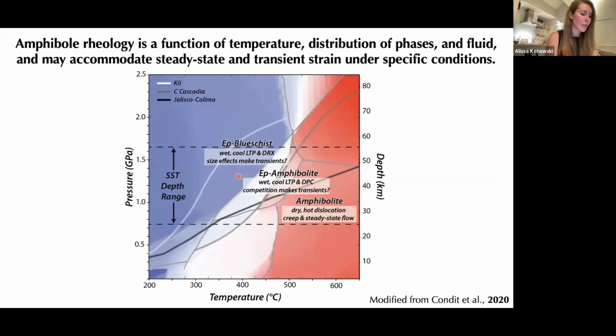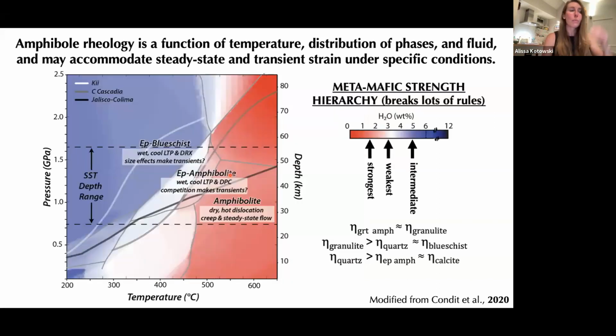So now I'll just wrap up quickly with what we've learned. I hope I convinced you that amphibole rheology is a function of temperature, distributions of phases, and water content. For the highest temperature samples, we have dry, hot dislocation creep that may facilitate steady state flow, while the other colder amphiboles with evidence for low temperature plasticity and diffusion accommodated deformation as well might actually be more favorable to produce stress gradients at the microscale.